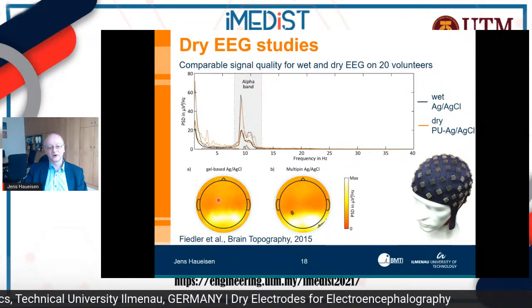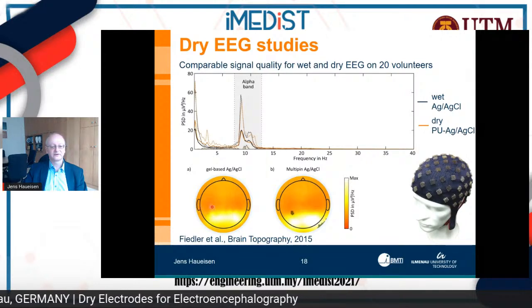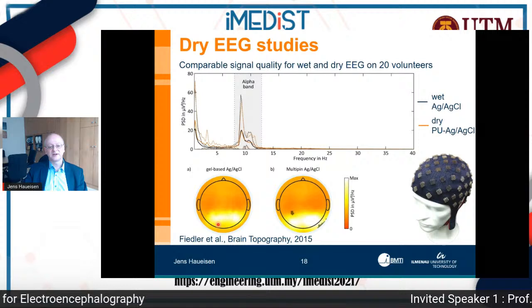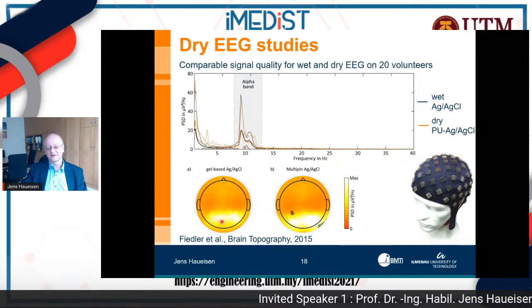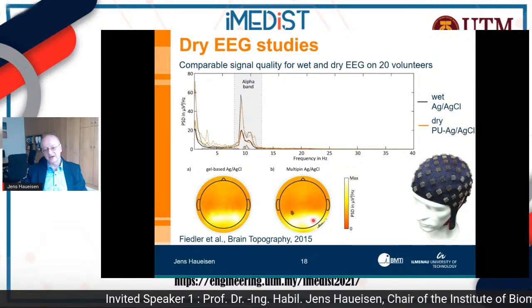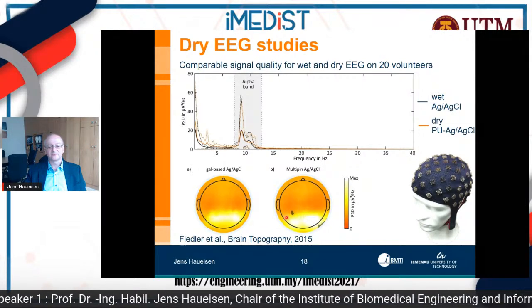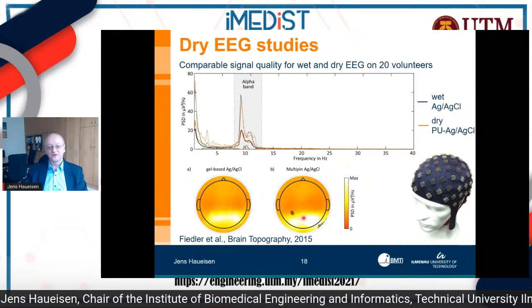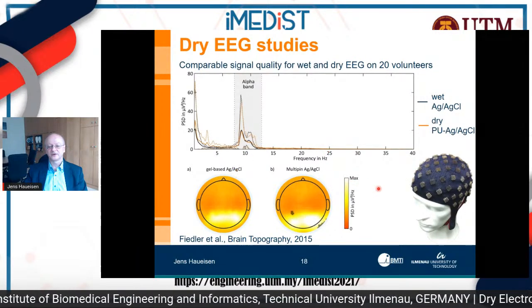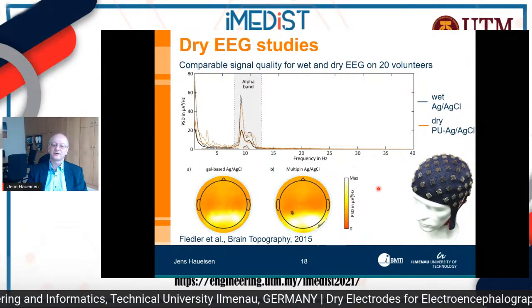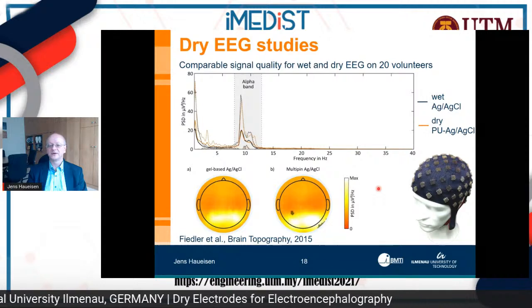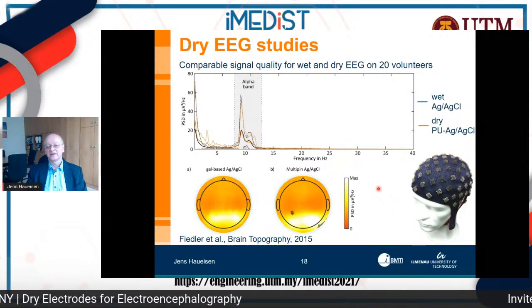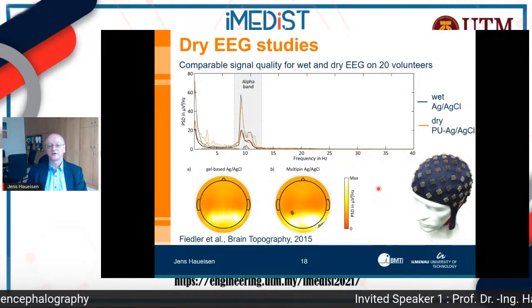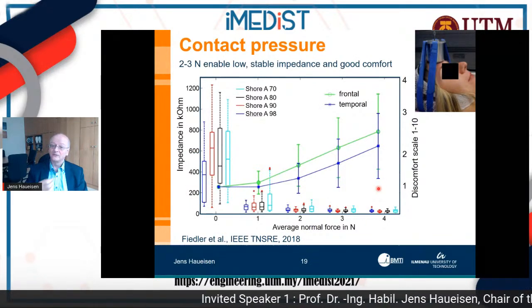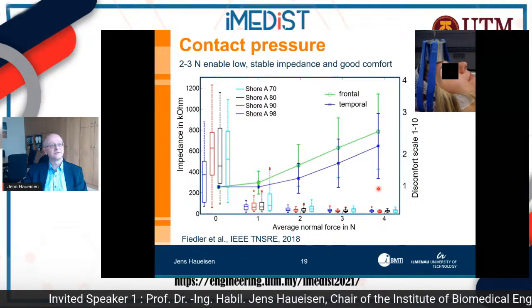So in terms of topographies, so we look from the top onto the head, ears, left and right, nose in the front, and you see that we have here very nice activity over the back part of the head. And this is actually the same for both wet and dry. Now with this first measurement test here, which I show you here, we had some issues with contact pressure, because not in all subjects we were observing a perfect contact pressure. And this made us having a look at contact pressure and comfort, because also some subjects complained those pins are a bit too hard. I don't feel comfortable with this.